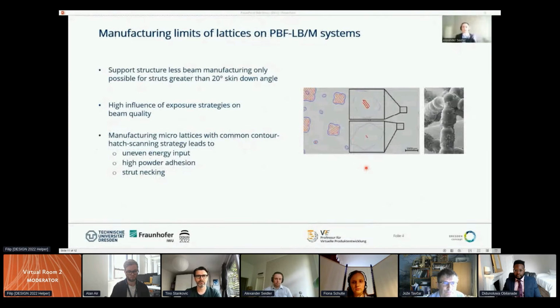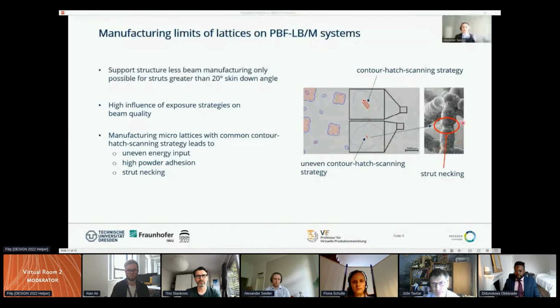So for a support structure-free production of microlattice, which is needed, only a beam orientation of more than 20 degrees skin-down angle can be manufactured. So stiffening approaches such as those according to Wang and Wu cannot be realized. In addition, microlattices cannot be produced with conventional contour hedge exposure strategies shown here, since numerical inaccuracies due to the mesh-based description in the scan strategies lead to uneven energy input in the printing process, which results in necking effects of the beam as well as strong powder adhesions.